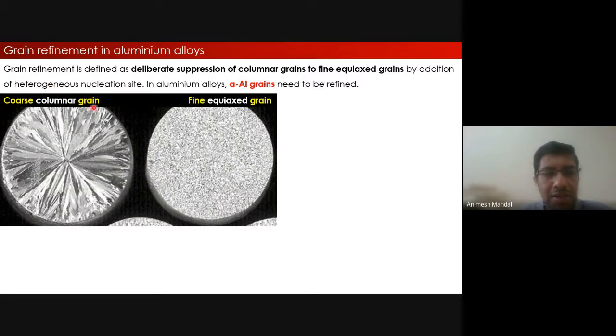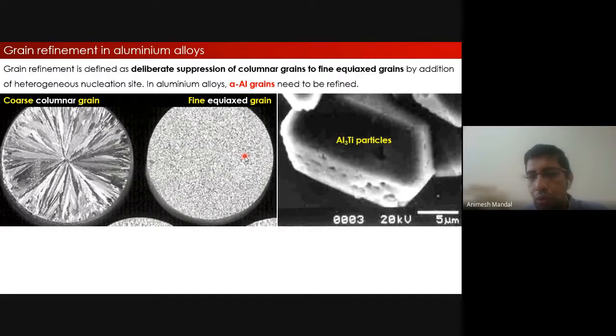For example, this type of grains we call coarse columnar grains. So how does this transformation occur in the first place? It's not going to happen on its own. You need to add something to this molten alloy, that means to the molten aluminum alloy, and thereafter, after solidification, you can expect this type of grains. So what is to be added? Certain particles, like Al3Ti in aluminum.